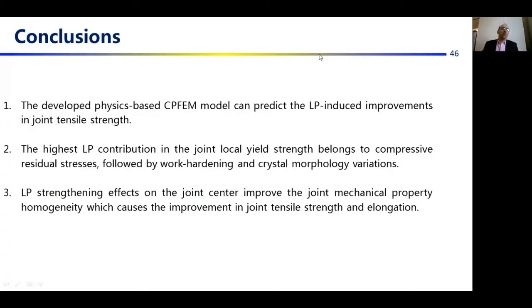For the overall conclusion, the developed physics-based CPFEM model can predict the laser peening-induced improvement in joint tensile strength. The highest laser peening contribution in joint local yield strength belongs to compressive residual stresses, followed by work hardening and crystal morphology variations, and laser peening effects on the joint center improve the joint mechanical property homogeneity, which causes the improvement in both joint tensile elongation and strength.